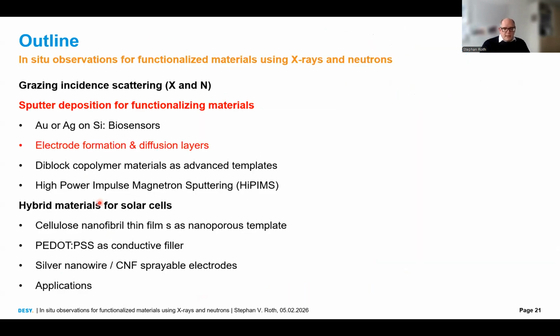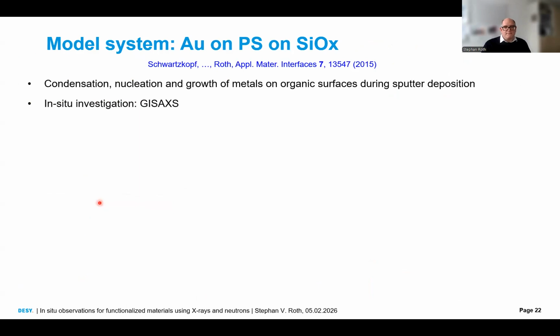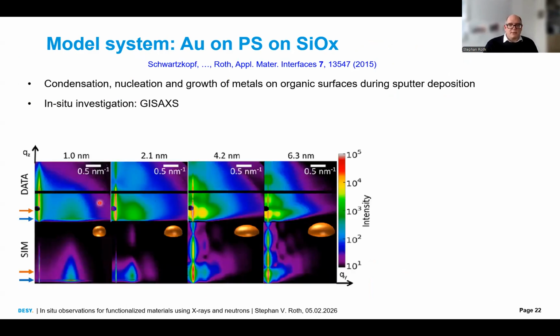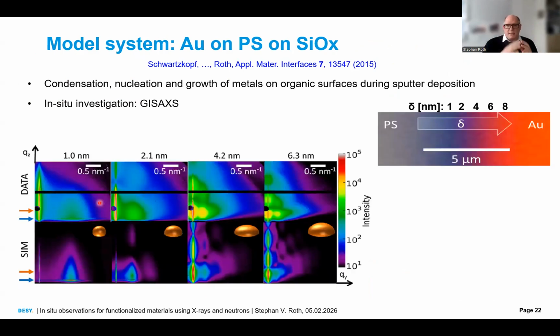Good. Now let's go to electrode formation and diffusion layers. So we start with a model system, gold on polystyrene on silicon oxide, spin coated. We do the same experiment as I've shown you beforehand, in situ deposition of gold on polystyrene, in situ GISAXS at the beamline. Here are shown selected GISAXS images, and here the corresponding simulations. And here you see already that we can even go to very fine detail.